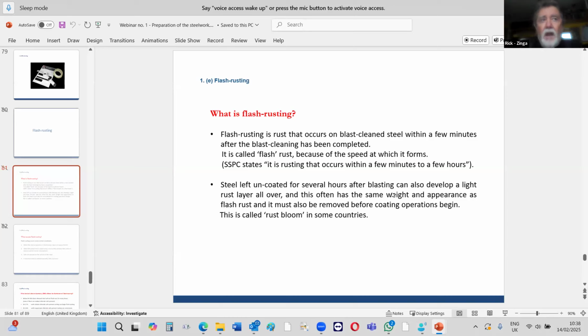We had one company that blasted 150 square meters. And by 4:30, 5 o'clock, they only coated 70 or 80 square meters. So of course, the next day it was flash rusted. But luckily, there had been very little overnight condensation. It was still wet, but again, it was a light grade. It only rusted the peaks. So I said to them, "You're very lucky. If that had been a medium grade, you'd have to water jet or reblast that whole area again."